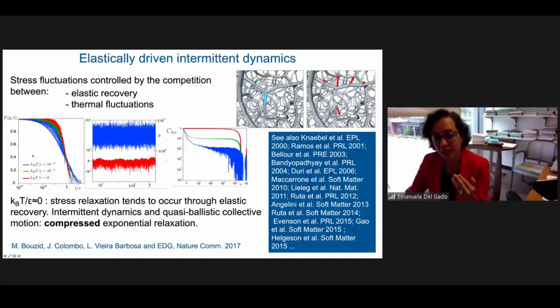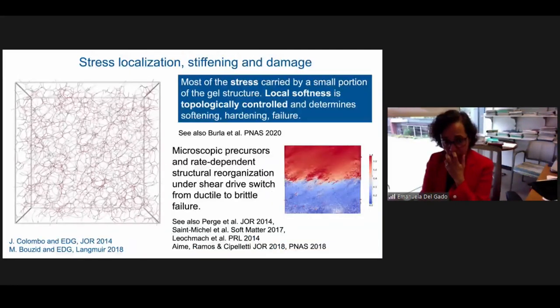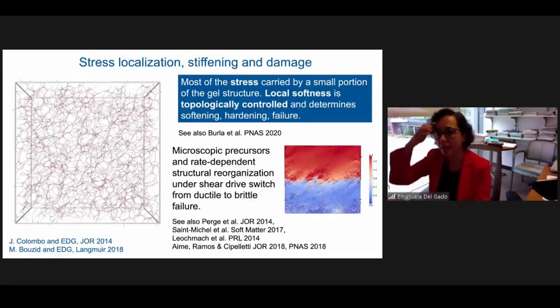And this is what we've seen in simulation, but in fact, it's been seen over, I would say, more than 20 years in a number of experiments, in a similar and wider range of gel materials and soft materials. The fact that there are subparts of the structure that play a crucial role, and this localized stress pattern, become even more evident if you now start to subject the material to deformation.